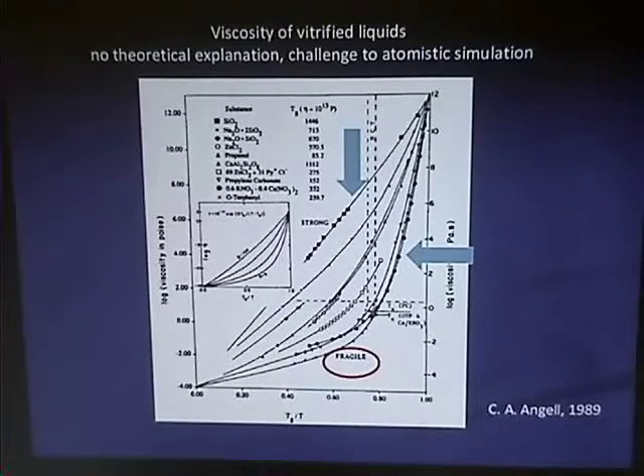And we actually have a theory that predicts those curves over the whole range - at least I like it as a candidate. And it's in the nature of the derivation that the theory doesn't just perfectly fit this Fulcher relation from the model. But the theory's applicability ends at TG, and so we think the extrapolation is still meaningful - as an experimentalist, from the model you extrapolate and determine that temperature. But you really do not expect, even from the model or in reality, to truly have a divergence.